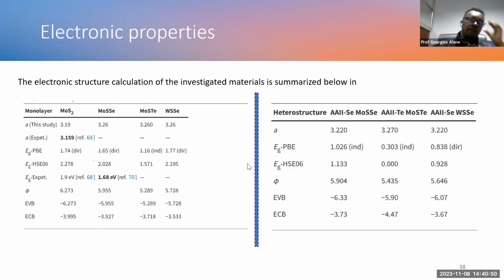And then what we have done is we investigated the electronic properties, like using PBE and HSE calculations. We calculated the band gap value, the work function, and the band edge values, valence band and conduction band edge values, as shown in this table, for the isolated monolayers.